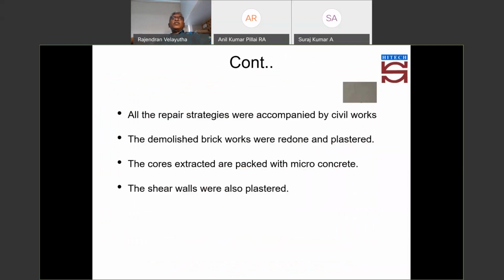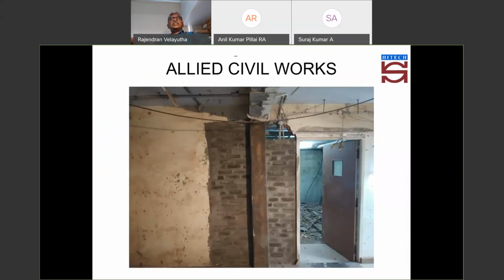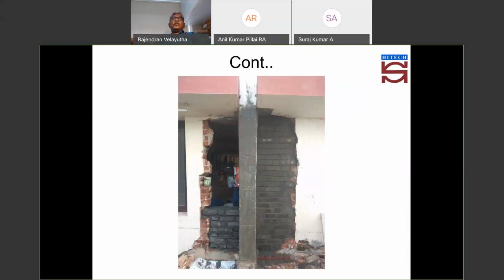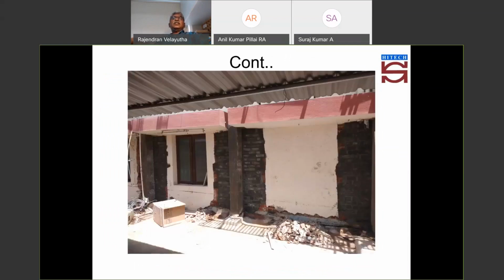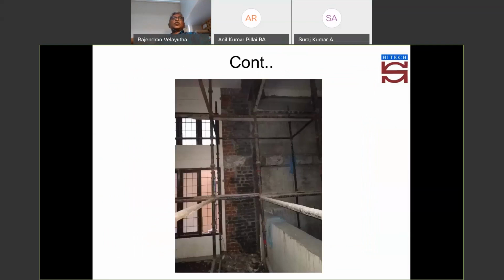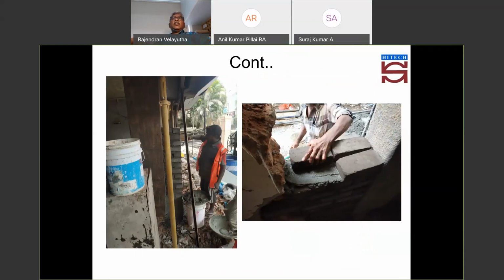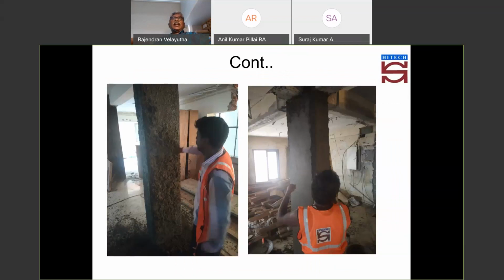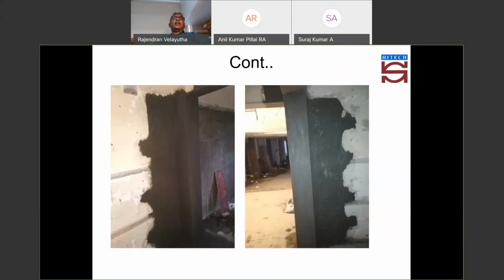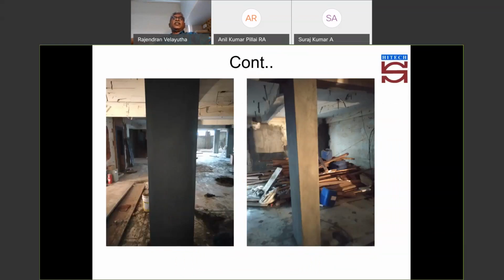Okay. When you are going for a CFRP wrapping, one of the biggest advantages is, even if you go for a 400 millimeter thick column, the repair system is going to have an additional thickness of just 2 mm only. When it is going to be 2 mm, you won't find at a later date whether the column has been rehabilitated or not. You will not be able to find it at all.